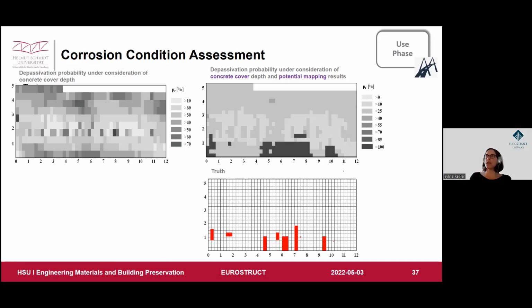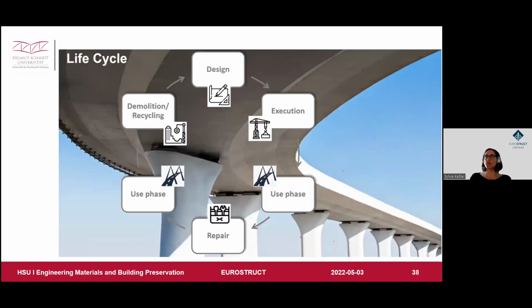And if you compare both, you can see here that it was a very good agreement between what we predicted as a high corrosion probability and what we really had as signs of corrosion at the reinforcement itself. So I'm really in favor of this method. This gives us really quantitative data on the corrosion condition of structures. So this is just a case study, and I want to move on because we still have to talk about one or two phases more.